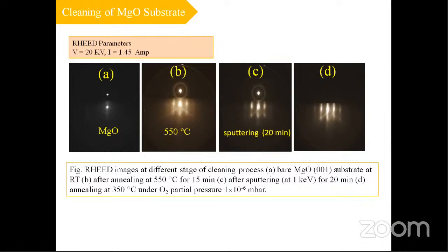Now, to further clean the surface, we sputtered with argon ion at 1 kV energy for 20 minutes. One can clearly see the spots are more visible as compared to the previous one. Since we know that after sputtering, the MgO surface may be oxygen deficient, to avoid this oxygen deficiency, we heated this substrate again at 350 degrees centigrade under oxygen partial pressure of 10^-6 millibar.